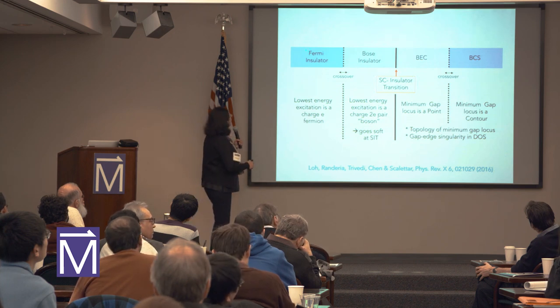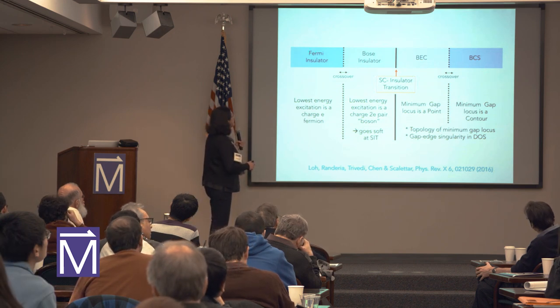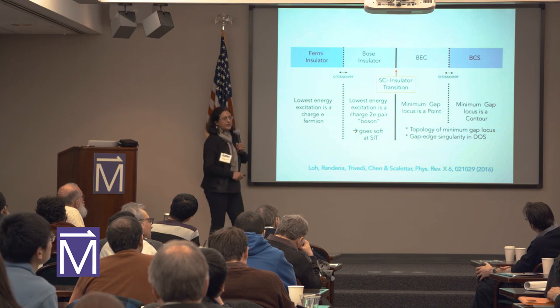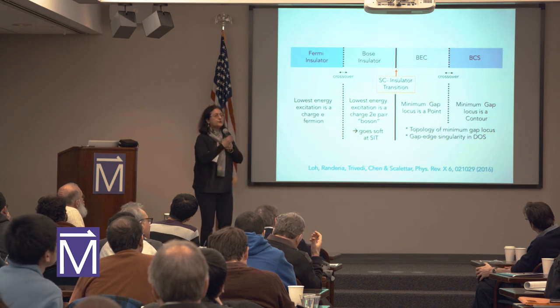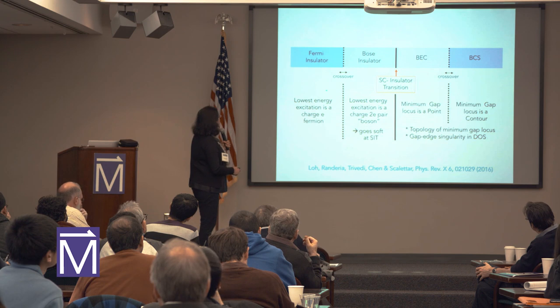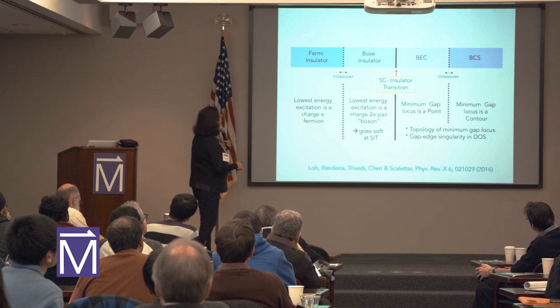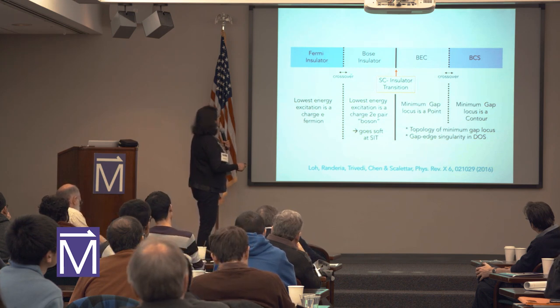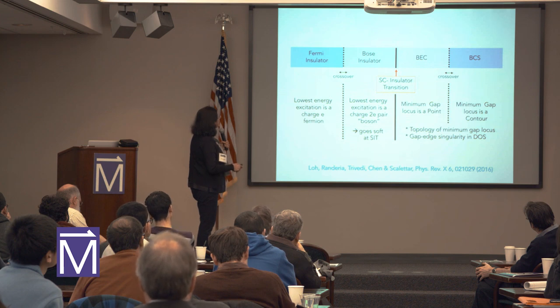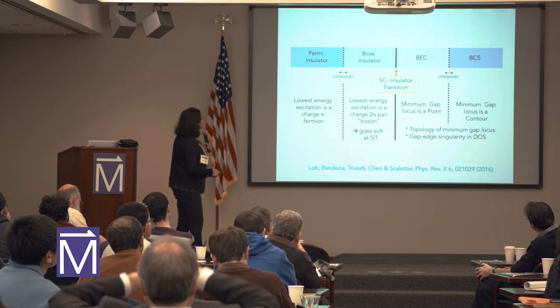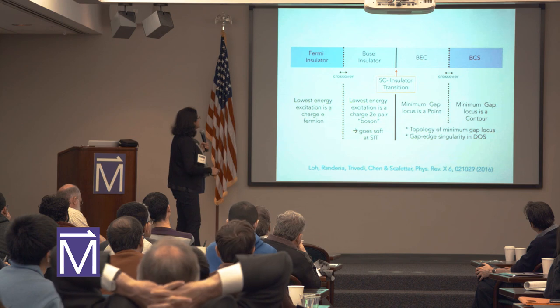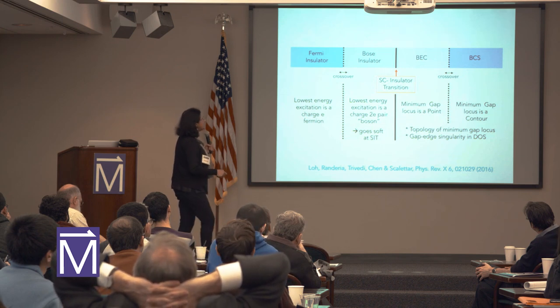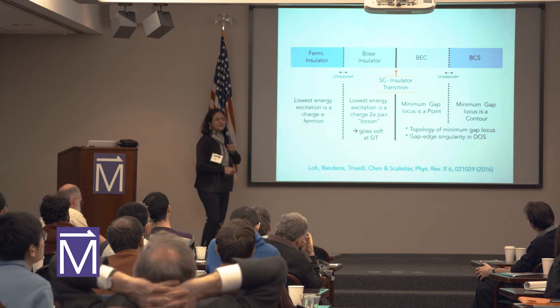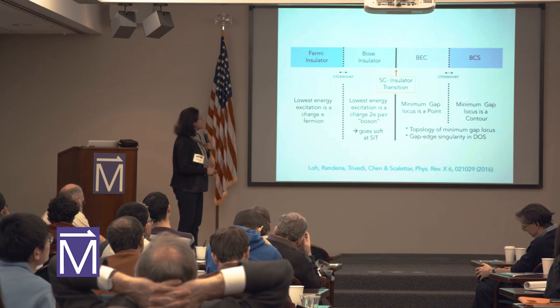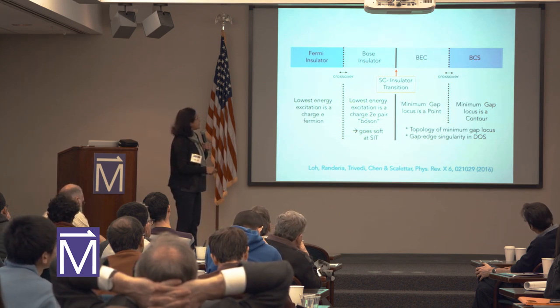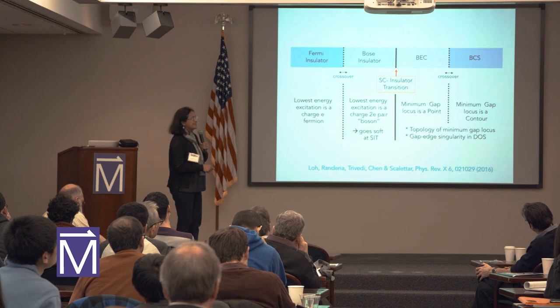So what we show is that there's no direct way to go from a Fermi insulator to a BCS superconductor. You have to go through two crossovers. The first is a crossover from a Fermi band insulator to a Bose insulator. And what distinguishes these two is that the lowest energy excitation is a charge e fermion. And here, the lowest energy excitation becomes a charge 2e boson. And that's what goes soft at the transition.